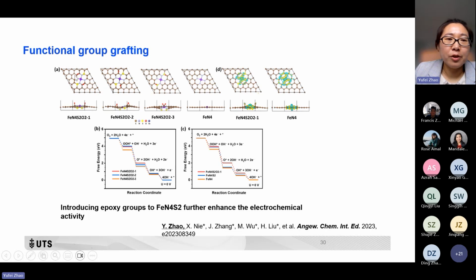So for the first 2 structures, we have calculated the ORR performance through the free energy. We found that structure 1 showed the best performance. We have also compared the performance of structure 1 to iron, nitrogen 4 and iron, nitrogen 4, sulfur 2. And structure 1 shows the best performance based on the DFT calculation. So we found that further incorporating this epoxy group can further enhance the electrochemical performance of the ORR of this active center. And also the position of this epoxy group is important for the ORR performance.